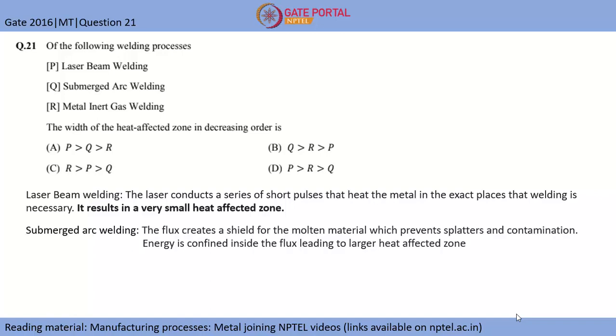The second one is submerged arc welding. Here we use flux to isolate the molten material, which prevents splatter and contamination of the joint. The energy is confined inside the flux, leading to a large heat affected zone. And this flux is basically of oxides, chlorides and so on, which are refractory materials. So considering the amount of energy you are putting into the joint, the heat extraction rate will decrease because of this refractory material. If the heat extraction rate decreases, the heat will be conducted through the two welding pieces. Hence a larger heat affected zone will occur in submerged arc welding than in laser beam welding.